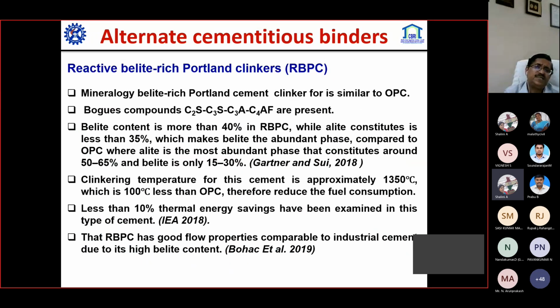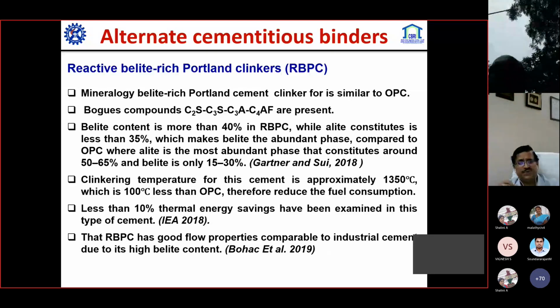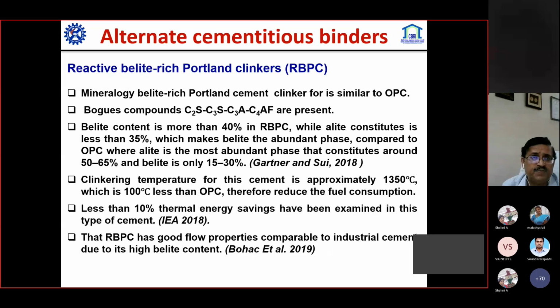Another is belite rich Portland clinker. It has been invented in China, and several other countries have started looking into it. Mineralogically, it is similar to ordinary Portland cement but a little different, because the belite content is higher in this cement. By this, our energy demand is reduced, as the clinkering temperature drops from a maximum of 1450 degrees centigrade to only 1300 to 1350 degrees centigrade, and overall energy saving is more than 10%. Overall its properties are good, and a lot of high belite cement is being used all over China. A few manufacturers are producing and utilizing it.